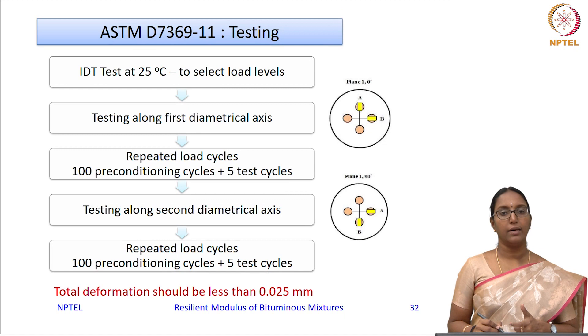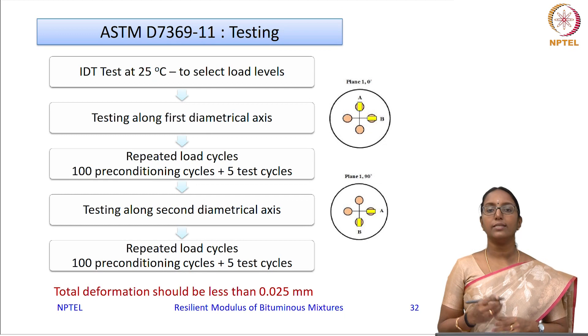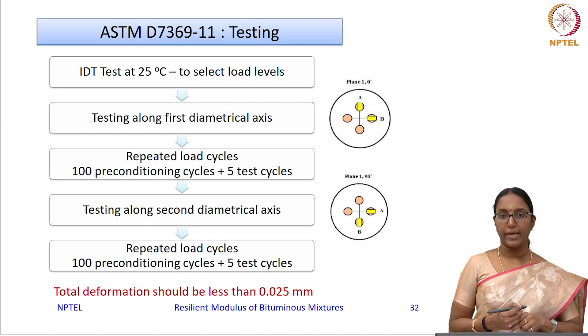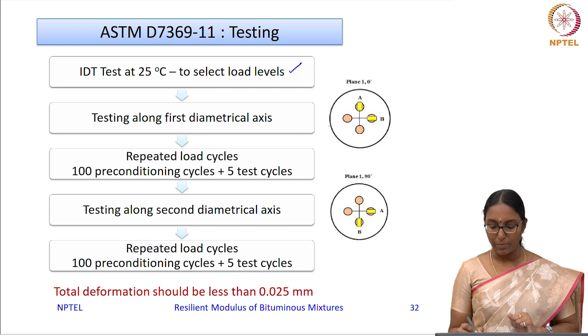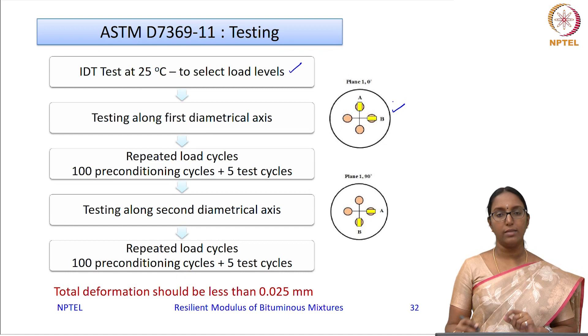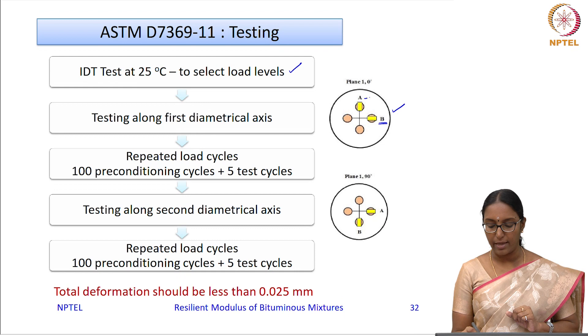The test procedure begins with conducting an indirect tensile strength test on a similar specimen at 25 degrees Celsius to find the ITS. Ten to 20 percent of that value is taken as the applied load P max. The LVDTs are placed and testing is first conducted along the first diametral axis — the 0-degree arrangement — with LVDT B in the horizontal direction and LVDT A in the vertical direction.